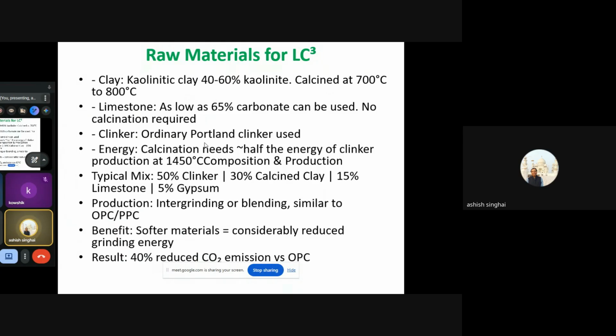So that says it all. A typical mix would be 50% clinker, 30% calcined clay, and 15% limestone, plus 5% gypsum as a set retarder to control the setting time parameters. What is the production methodology? Intergrinding or blending, similar to OPC and PPC. So we simply convert all three into powder form, either by intergrinding or by bringing these powders in separately and blending, and then it is ready for dispatch.